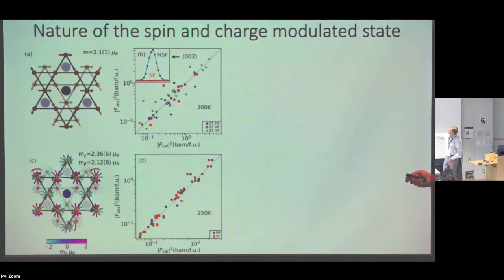So what's happening is that this antichiral state is actually rotating from plane to plane. As I come out along the z-axis, all of the spins are rotated by some amount. They actually rotate together, and this is why I'm looking at it as if I'm looking from above. But in addition, there's actually a component of the spin which is coming out of the plane along the z-axis.